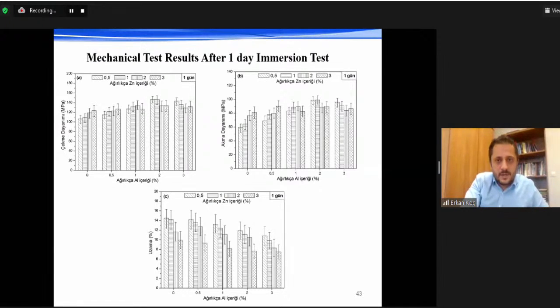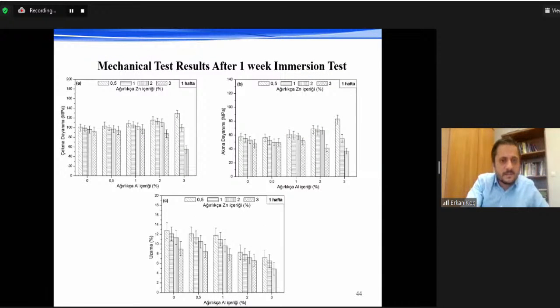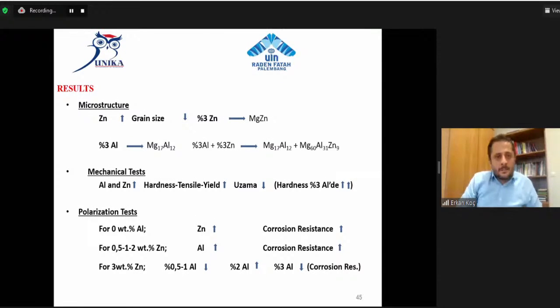Mechanical test results after 1 day immersion test and after 1 week immersion test, and results of microstructure: if the amount of zinc increases, grain size decreases. And if you use 3 weight% aluminum, intermetallic phases occur and decrease the mechanical strength. Aluminum and zinc increase hardness and tensile yield strength, but elongation is decreased. Polarization test.